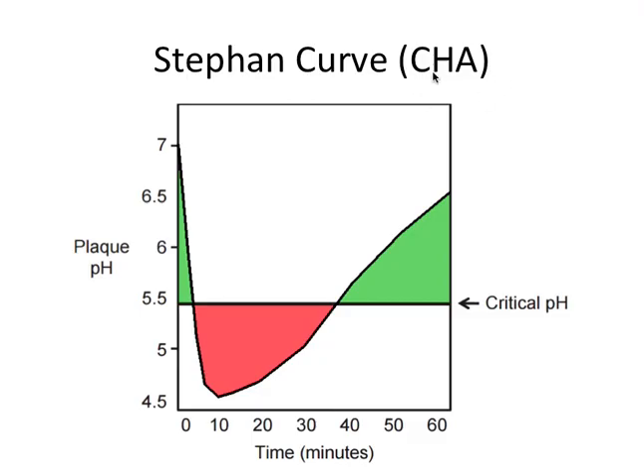Carbonate-substituted hydroxyapatite, or CHA, has a critical pH around 5.5, though there are variations among individuals depending on exact concentrations of calcium, phosphate, and carbonate. Dentin and cementum, however, fall somewhere around 6.7 — maybe a range of 6.2 to 7. This is why, if you have an exposed root surface where cementum or dentin is exposed to the mouth, those surfaces are more susceptible to acid erosion and decay. Because the critical pH is so much higher, there would be far more area under the curve in red, meaning a lot more demineralization occurring a lot more frequently.